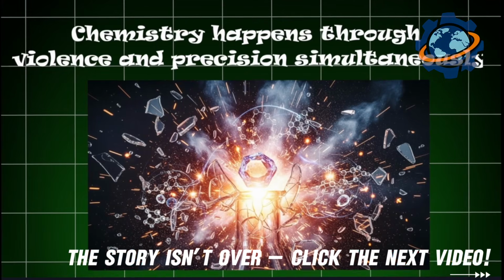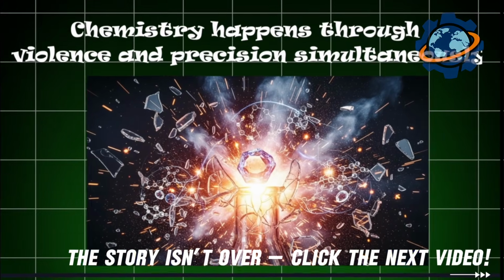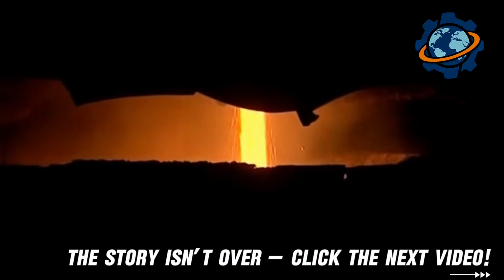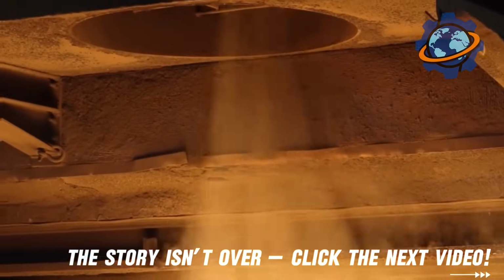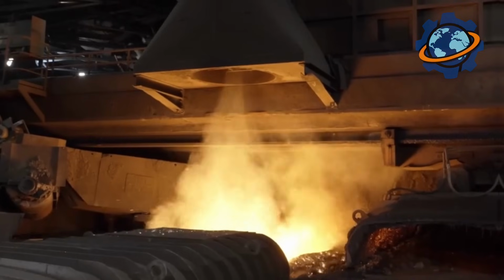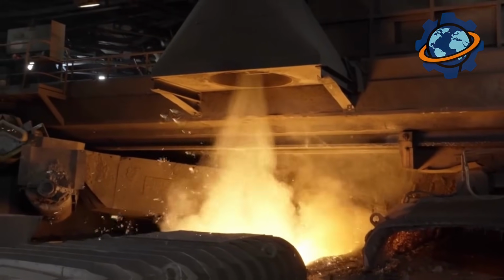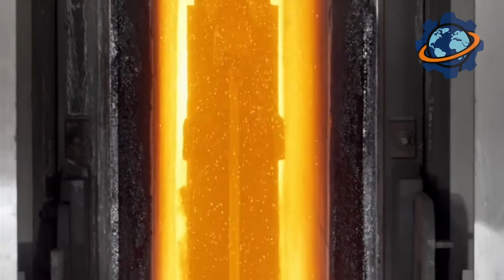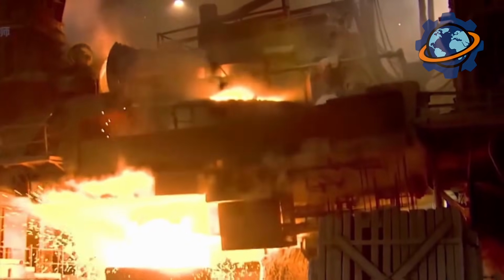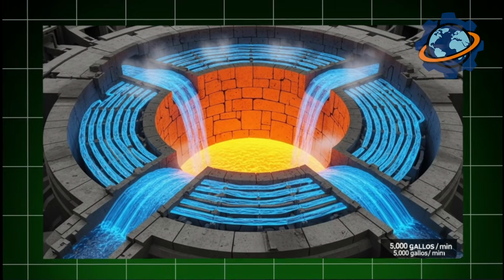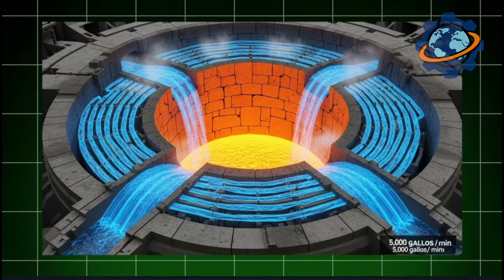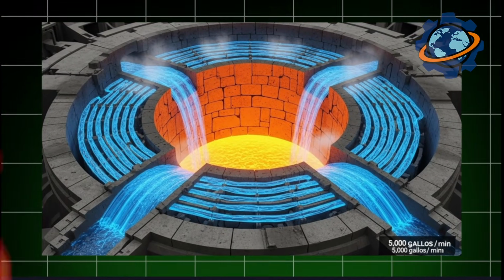Chemistry happens through violence and precision simultaneously. Oxygen lances inject pure oxygen into molten steel at supersonic speeds. The oxygen burns impurities, carbon, sulfur, phosphorus, creating slag that floats atop the denser steel. Temperature reaches 5,800 degrees at plasma core, hot enough to vaporize iron itself. Cooling water circulates through furnace walls at 5,000 gallons per minute, preventing meltdown.